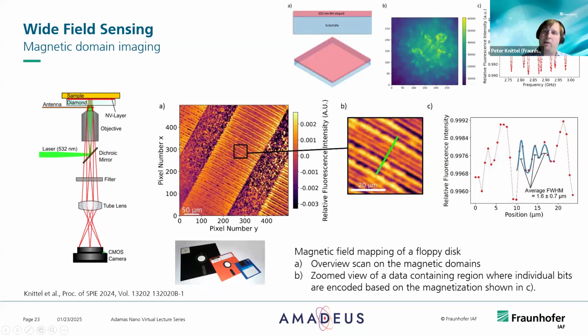And what you see here is an ODMR scan that actually contains all 4 orientations of the NV center. And making use of these 4 orientations, you can even get vectorial information of a sample that you measure that is directly put on top. So a standard configuration to measure something like this is shown here on the left-hand side. And basically you have the diamond with the thin layer sample on top, and you use a CMOS camera to detect in parallel on several pixels the luminescence intensity, and with that you can get direct information on the magnetization.